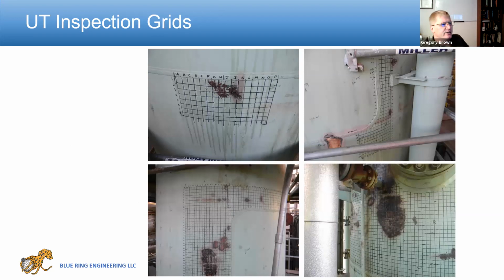So what you're looking at is the 4 locations. These are actual photographs. The grid you see was a manual grid used to do ultrasonic inspection. The inspector drew the grid out and then did straight or compressive ultrasonics at each location to get a wall thickness measurement. Ultrasonics works really well to get thickness measurements, but you need to have access to the surface, you need a clean surface, etc. It doesn't work through things like insulation, so you need to look at other methods for that.